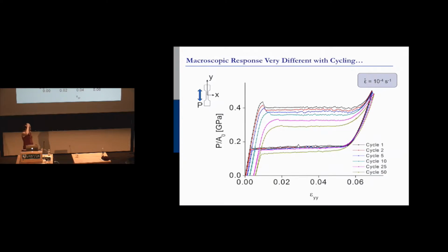So then the question was, okay, how does this change in cycling? We picked a material that had a huge change in cycling because we wanted to make it really obvious. So here's the nickel titanium material, and we looked at it from cycle 1 to cycle 50. Each one of these dots is an image that has 500,000 strain values that you saw before, that are all averaged to produce one strain value and then plotted versus the applied stress. Okay? So each one of these dots represents an image.